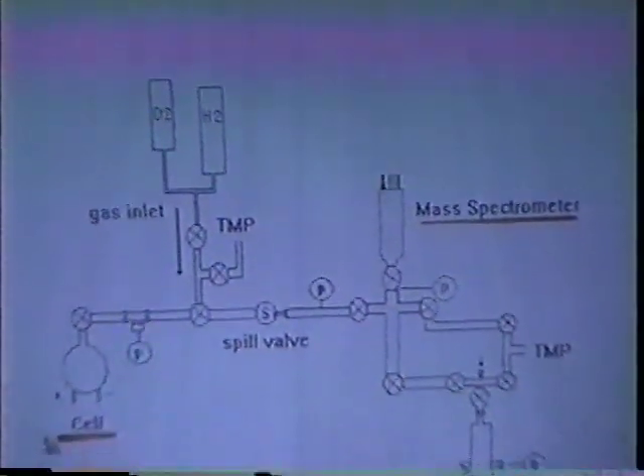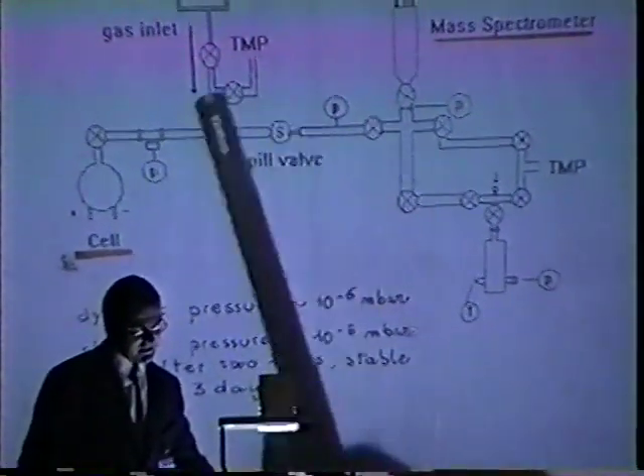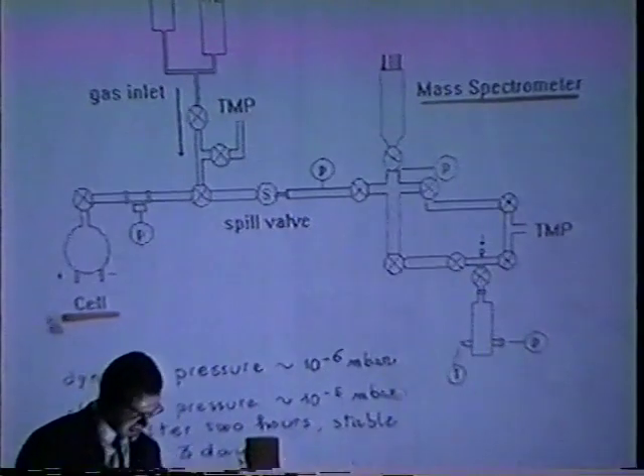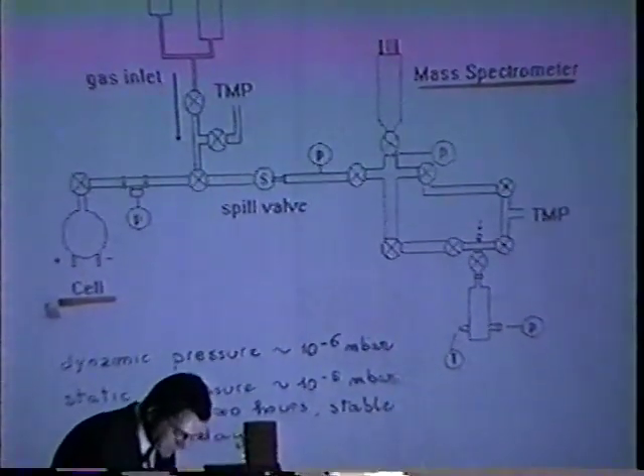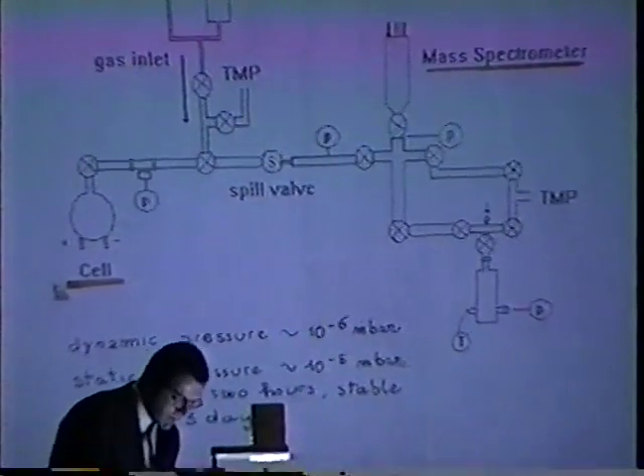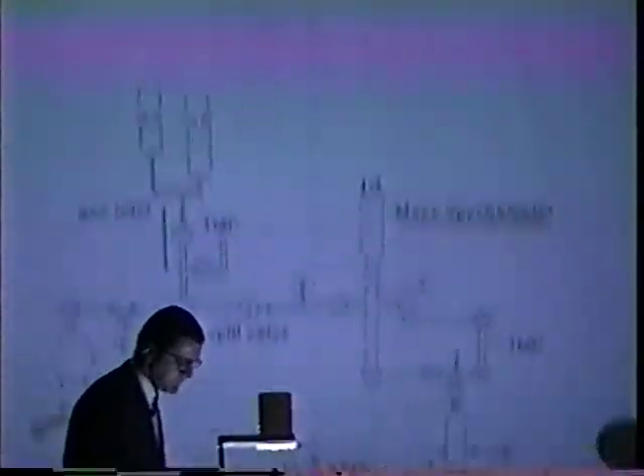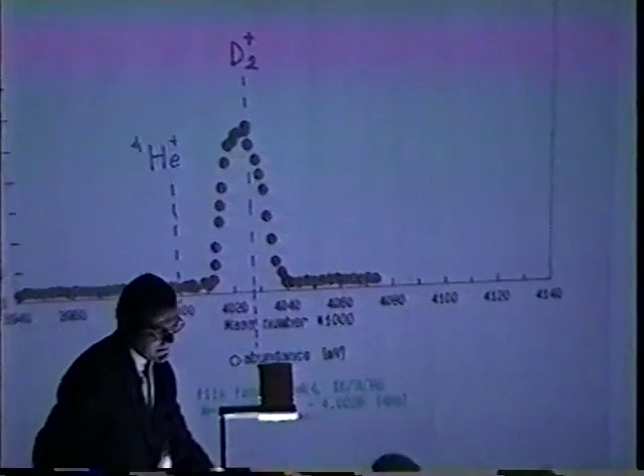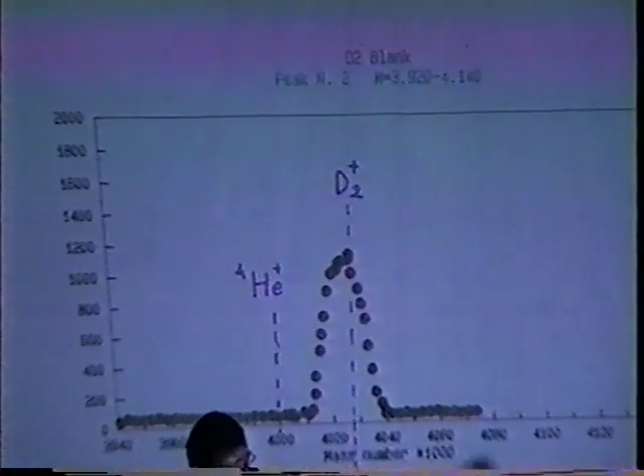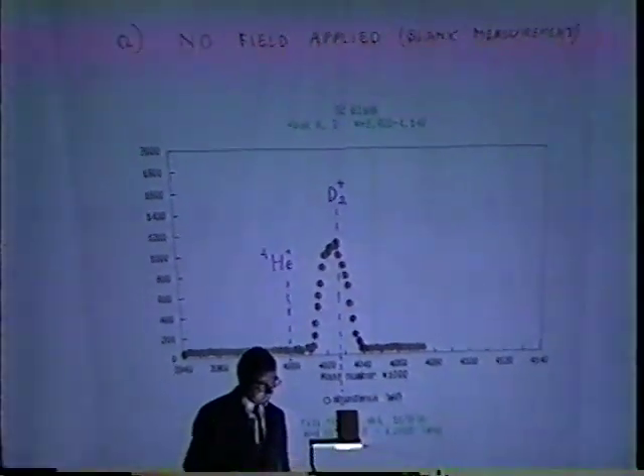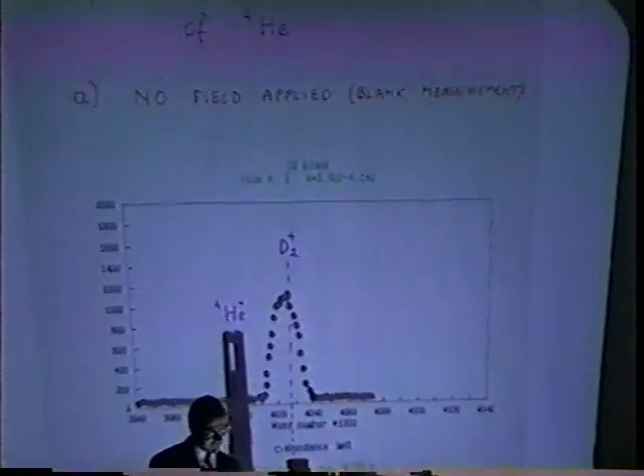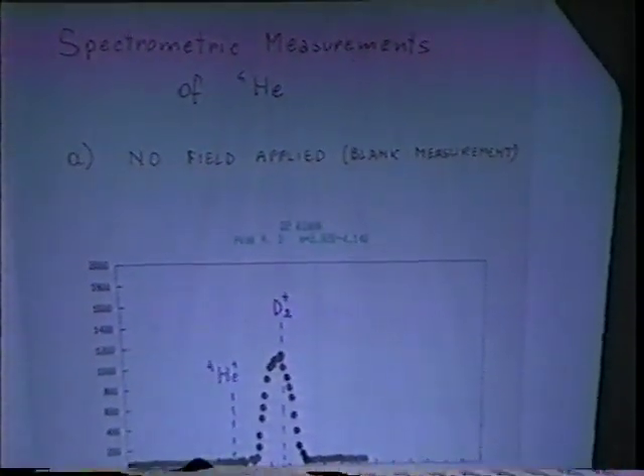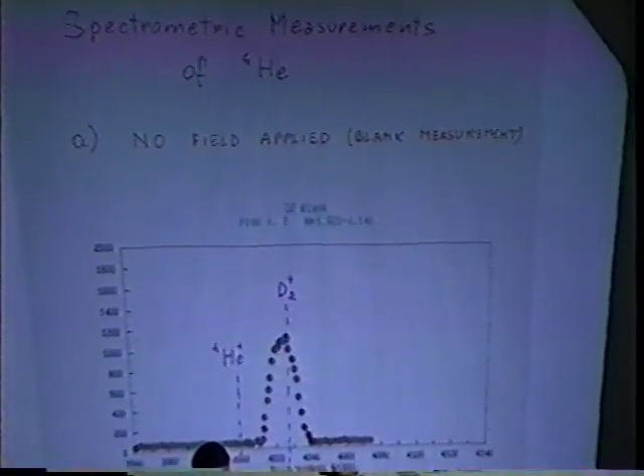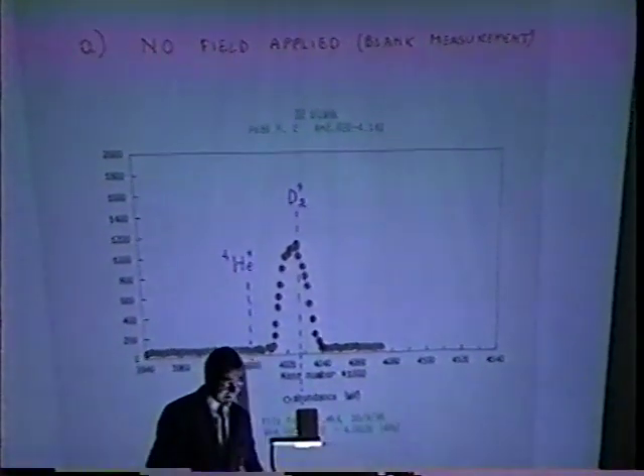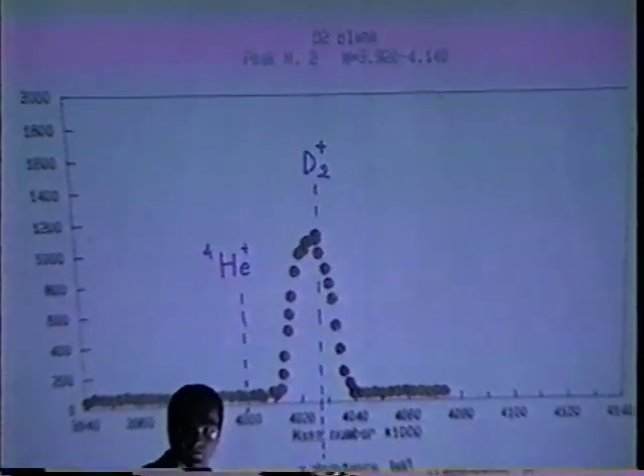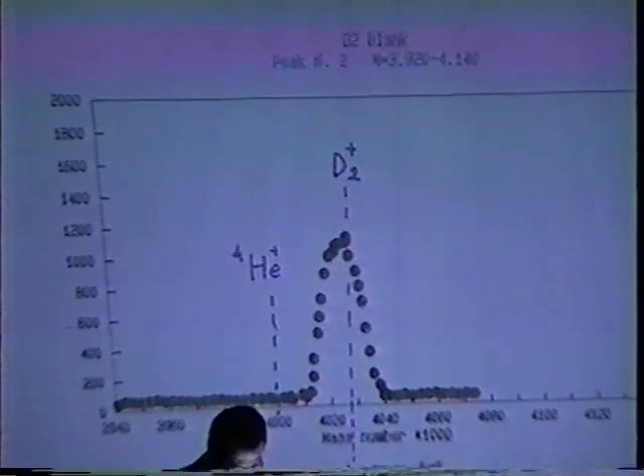What we obtained sending the deuterium gas staying in this side of the circuit to the mass spectrometer was this: a peak corresponding to deuterium and absence of helium-4 in the region of interest. As I said before, no higher than 0.5 per thousand content in the analyzed gas.